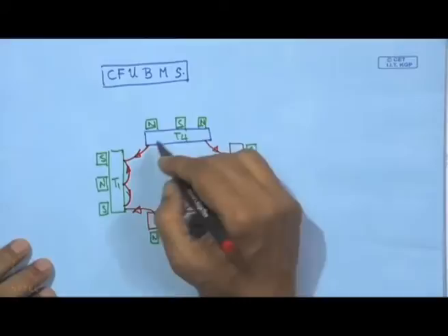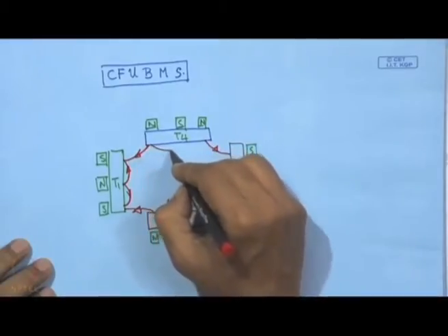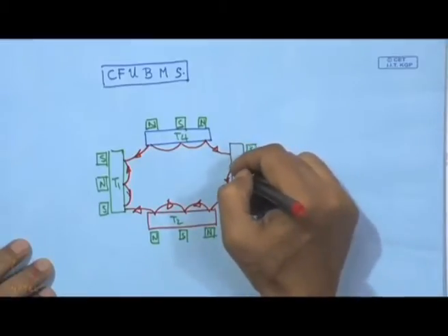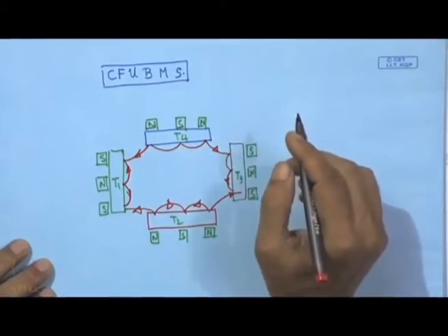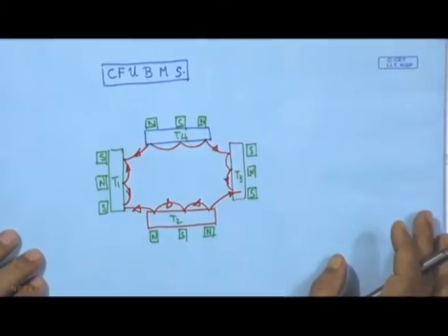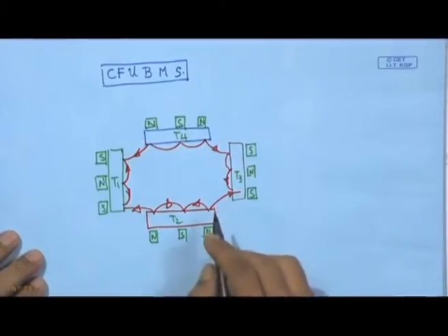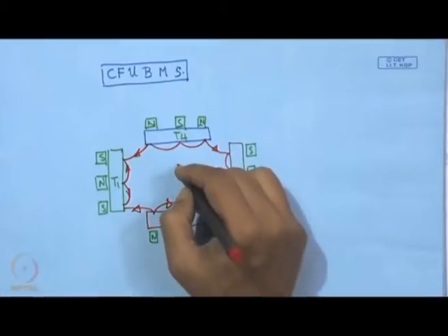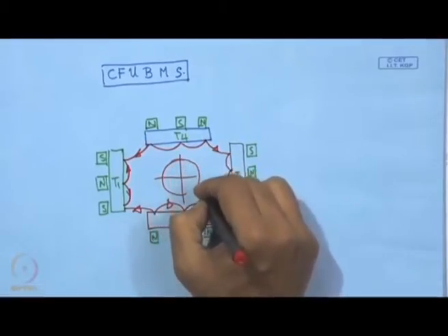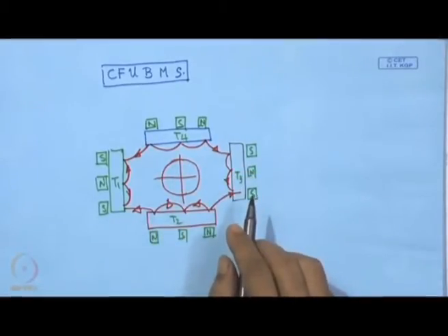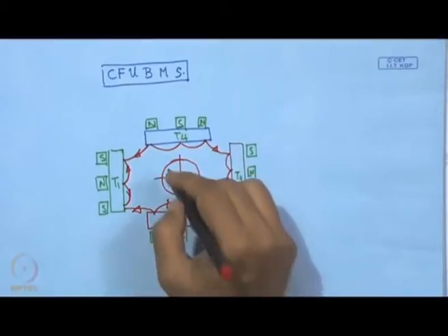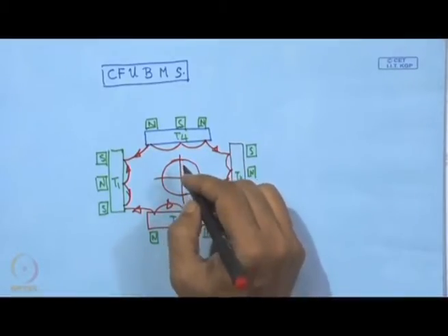So, we get a huge plasma volume, and within that we expect to have a plasma with high density and uniformity of the density, and in this case one can put a rotary table on this surface, and with that we can have a large volume of parts.